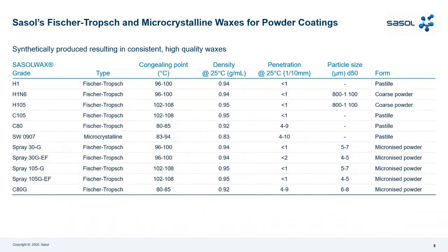Here is the portfolio of Sasol Wax, Fischer-Tropsch and microcrystalline, an overview of our waxes. You can see that there are two types of wax, Fischer-Tropsch and microcrystalline. We can see different congealing points: from 96 to 100, then from 102 to 108, from 80 to 85 for the C80 Fischer-Tropsch, 83 to 94 for the microcrystalline, and then we have the other micronized powders.